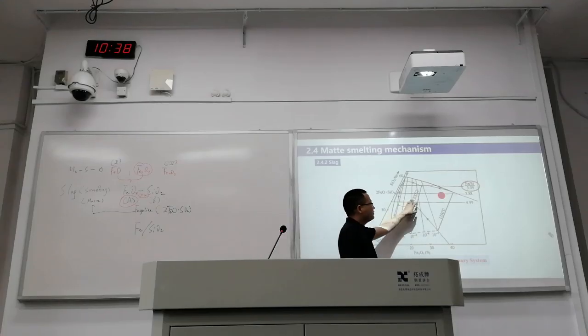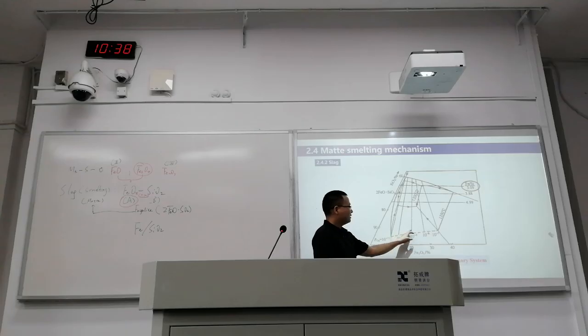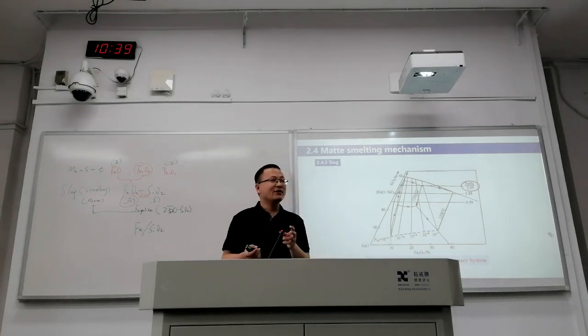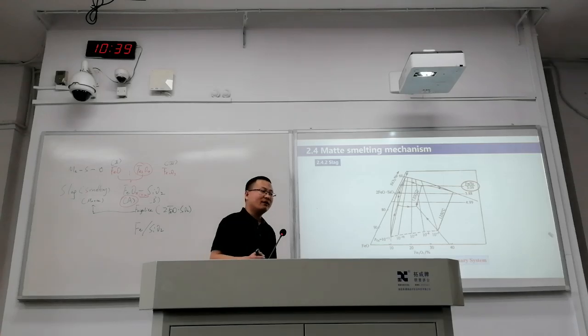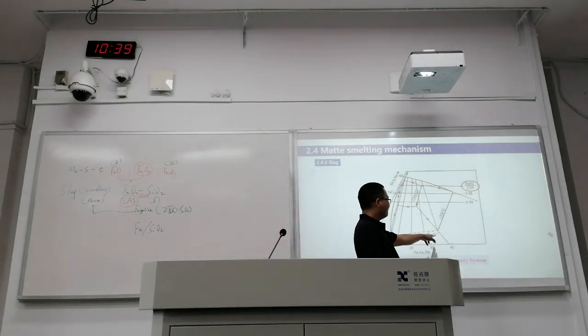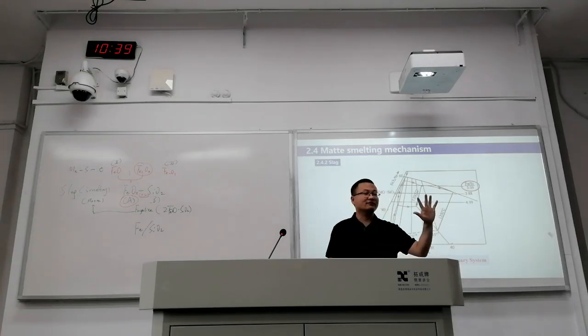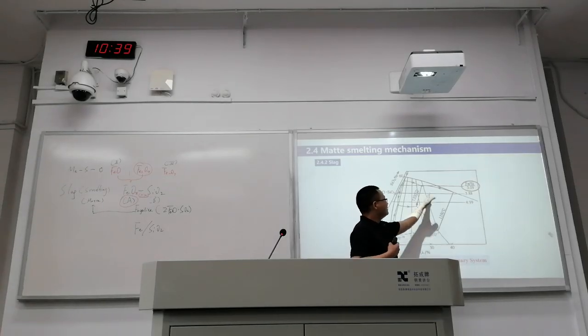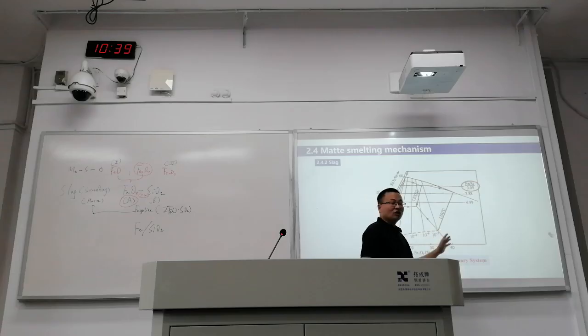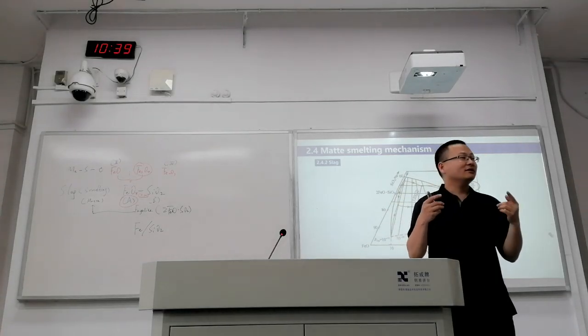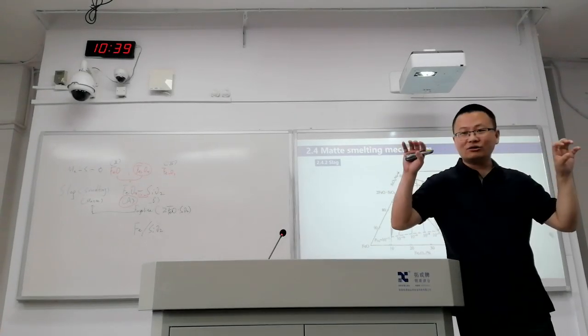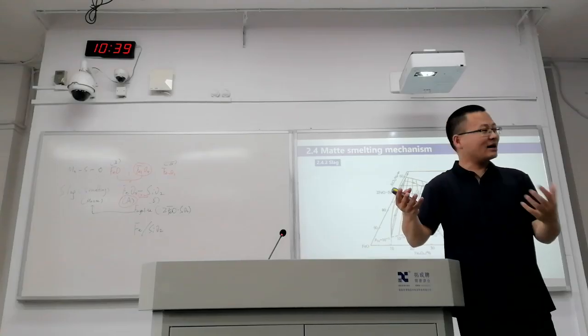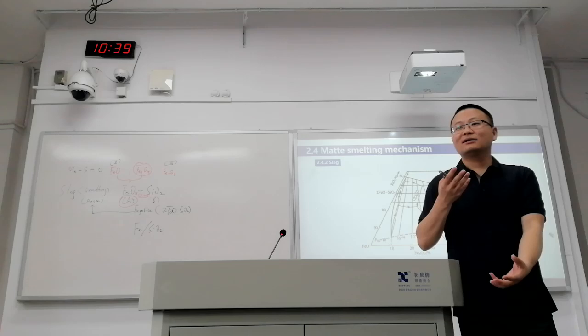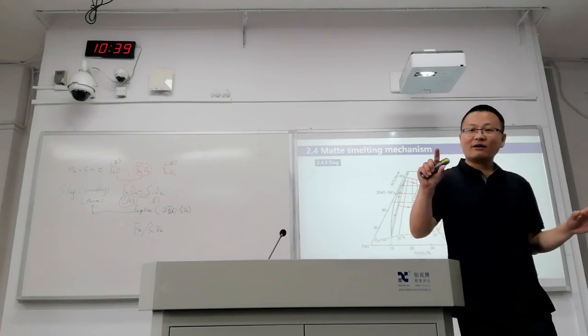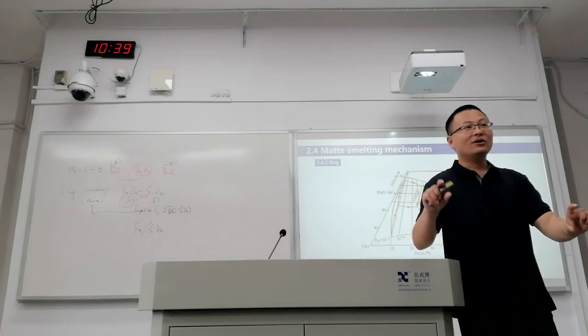And besides the liquidus temperature, besides the iron silica ratio, another important line is the oxygen potential. You know that we have already discussed, when we are producing copper, the oxygen potential will be 10 to the -7, -6, -5. So they are our options. So the oxygen potential should meet my requirement, and the liquidus temperature should meet my requirement. These two should match. When you have these two, you are running the furnace with melting slag, and you are getting liquid copper at the bottom of the furnace. Otherwise, you are losing something. Either the slag will freeze, or you are not getting copper.